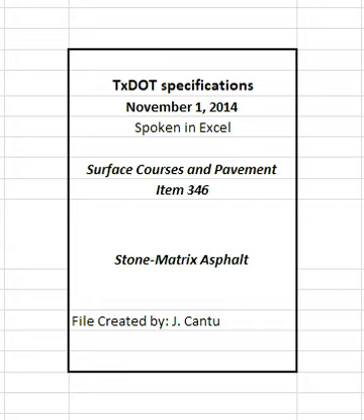Provide the equipment and means to obtain and trim roadway cores on site. On site is defined as in close proximity to where the cores are taken. Obtain the cores within 1 working day of the time the placement sublot is completed unless otherwise approved. Obtain 2 6-inch diameter cores side by side from within 1 foot of the random location provided for the placement sublot. Mark the cores for identification, measure, and record the untrimmed core height, and provide the information to the engineer. The engineer will witness the coring operation and measurement of the core thickness.